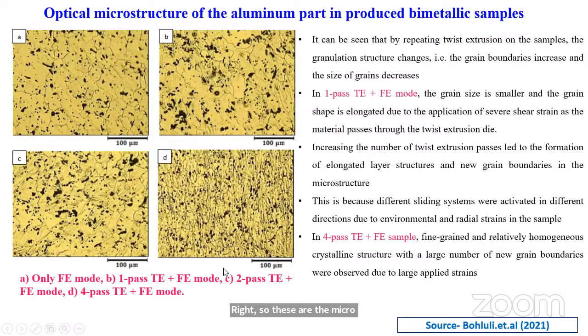Okay, the fine grain microstructure is obtained after 4 pass twist extrusion and 1 forward extrusion mode. The grains are homogeneously distributed and mixed, which induces high strength and homogeneity in the sample.